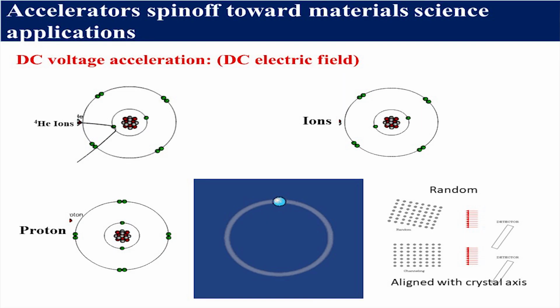After backscattering, we can calculate the energy of the ions, and we have the formula to calculate the target atom. A simple elastic collision can be applied here, and we can know which atom is in front of this ion. Every atom has different energies. They are the fingerprint of that atom. So we can identify the target atoms.